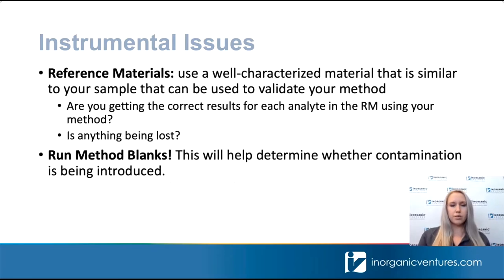Another thing we recommend is use of a reference material. An appropriate reference material is going to be a well-characterized material that is similar to your sample. And you're going to take that reference material and prepare it in the same way that you would prepare your sample to make sure that you're getting accurate results for all of your analytes. The reference material is going to be well characterized and have a certificate of analysis detailing the amount of each analyte in that reference material. So you can validate your method using this approach to make sure that you're not losing any analyte or adding any contamination during your process.